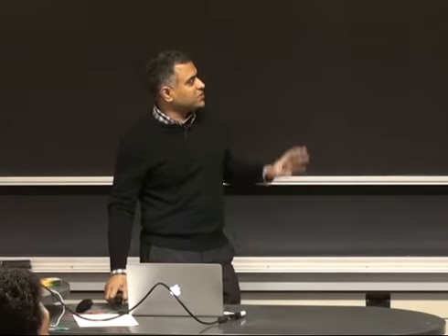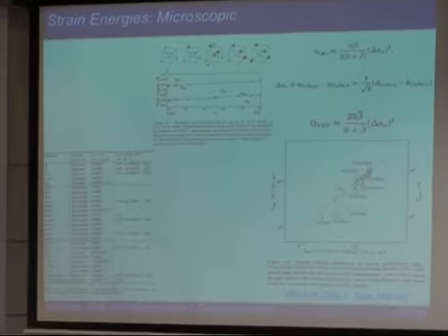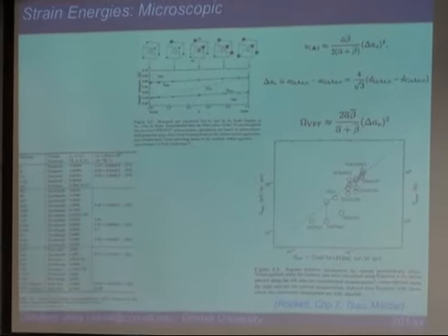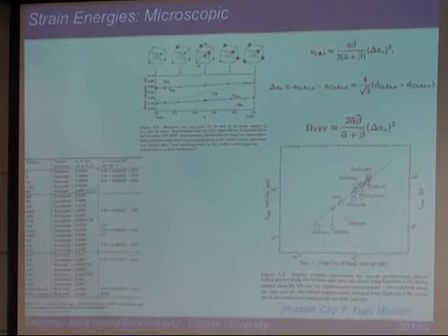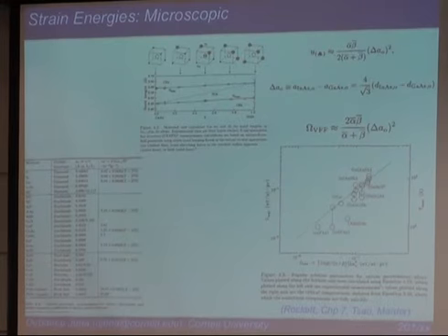Okay, so what we'll do today is, before I start, any questions? In the last class we looked at strain from a microscopic picture, and essentially we ended up with the very classical argument of energy being half k x squared, because of bond stretching and bond bending. You end up with a certain energy for an alloy, and the net energy that minimizes the formation of tetrahedra of different alloy compositions is given by this valence force field energy scale. That looks basically like a constant times delta x squared.